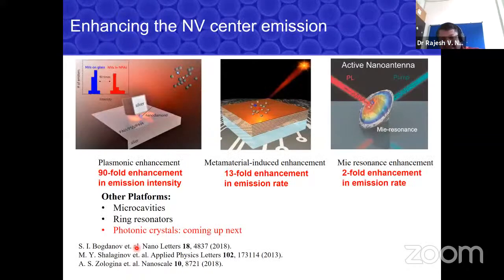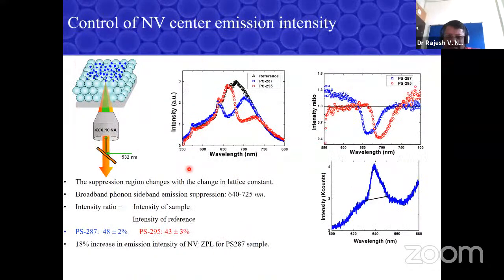So as I said in the previous slide, what we need is to isolate the zero phonon line, the pure electronic transitions, and suppress all the unwanted phonon sidebands. As you have seen in photonic crystals, when I talked in the initial slides, we are trying to suppress the emissions. There are different proposals recently in the literature using different kinds of photonic structures to suppress this phonon sideband and only get what you want, which is the zero phonon line. So we also did some experiments in this direction.